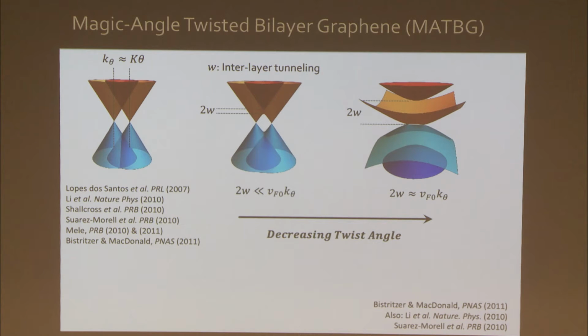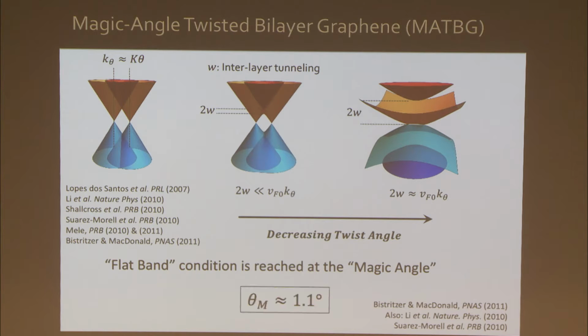This flat band condition is realized at an angle which was coined by Bistritzer and MacDonald as the magic angle. And it happens to be 1.1 degrees for graphene on top of graphene. Now, I should mention that there was very interesting theoretical work around the time, also by Suárez Morell, and experimental work by the group of Eva Andrei at Rutgers, where they did study a little bit the single particle physics aspects of this evolution of the electronic structure. They had already good indications that there would be this flat band, this electronic structure that would touch 0.